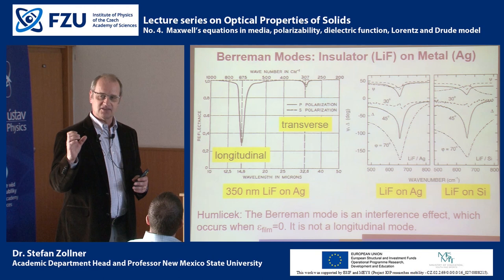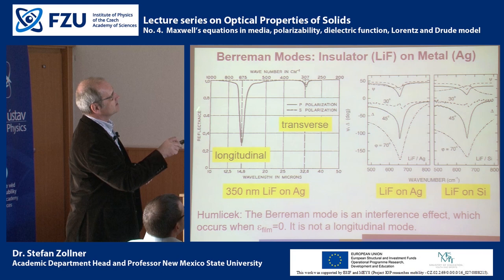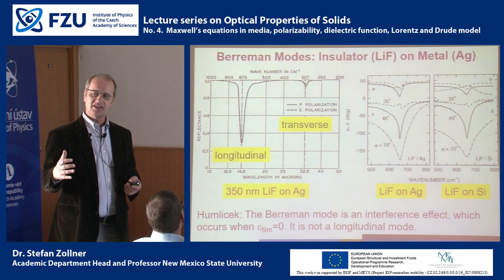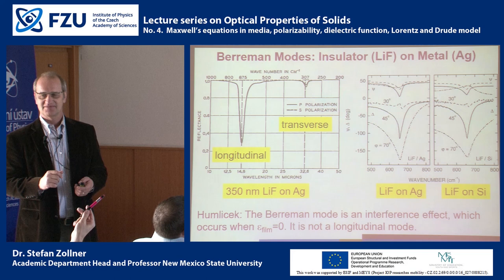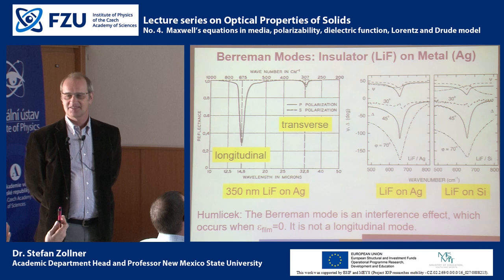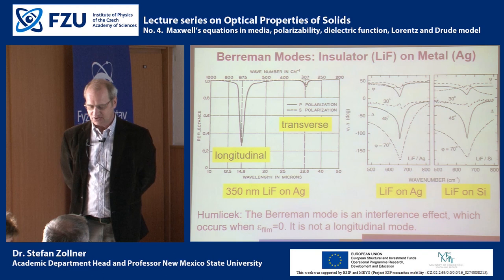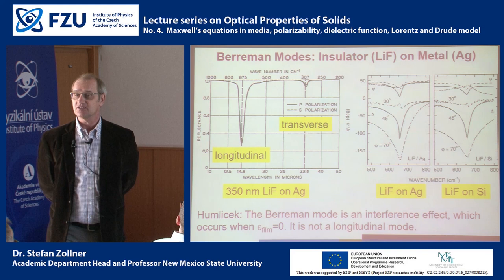If you have bulk lithium fluoride, you will not see this longitudinal mode. In order to see this longitudinal vibration, you must have a film on some sort of a different surface. If I measure bulk lithium fluoride, I will have one reflection band, and the high frequency edge will correspond to the longitudinal mode. Okay, so you're saying, well, yes, you can measure the longitudinal and the transverse waves from reflection. Yes, that is true. But if you do an absorption measurement, you will only see the transverse mode. You will not see the longitudinal mode.